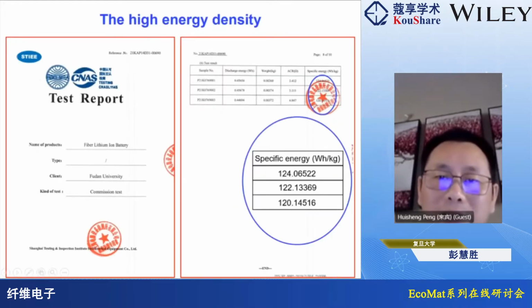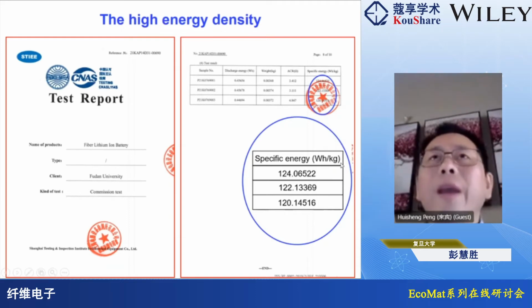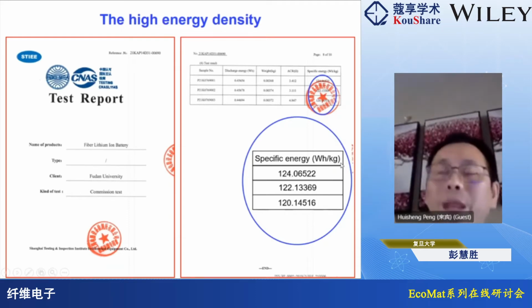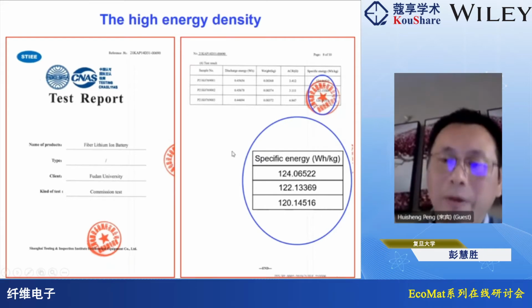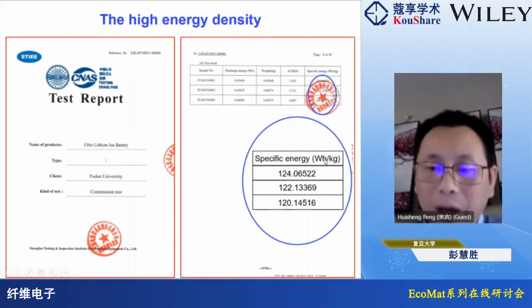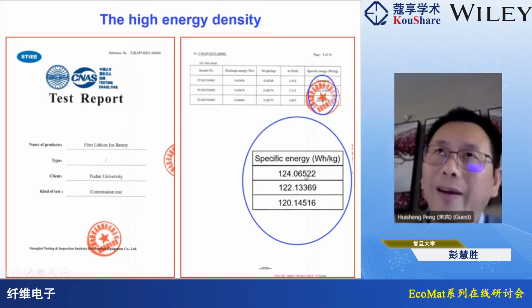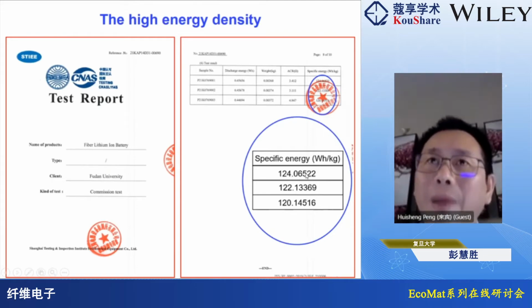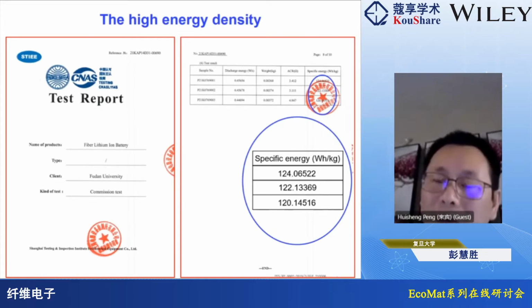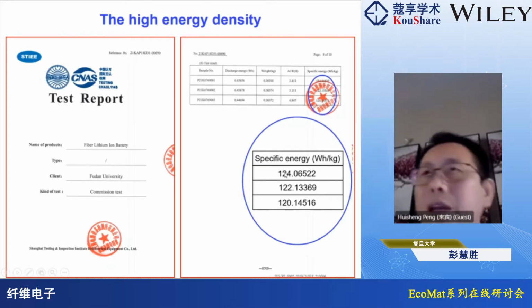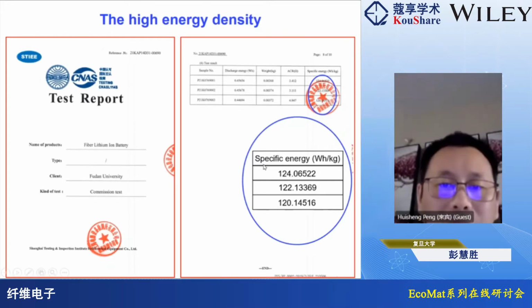And more importantly, the energy density can reach 124 watt-hour per kilogram, based on the whole fiber battery, so it's almost at the level of products. Although it looks lower than bulk batteries, we are still trying to increase it, and this value is good enough for many applications.